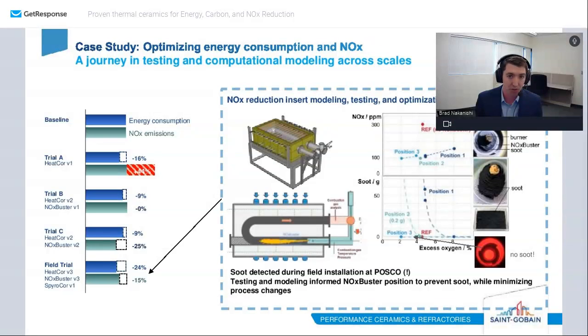However, long story short, Saint-Gobain's R&D teams were able to reproduce POSCO's conditions using our own pilot furnace at our R&D center in Paris, and then we conducted a series of tests and simulations to determine the root cause of the soot and develop a viable solution for POSCO. Together, POSCO and Saint-Gobain learned that managing the NOx buster position during the installation is very critical to prevent soot formation. And more importantly, we obtained a good solution that simplified the installation process for POSCO while having little to no impact on their furnace operations.